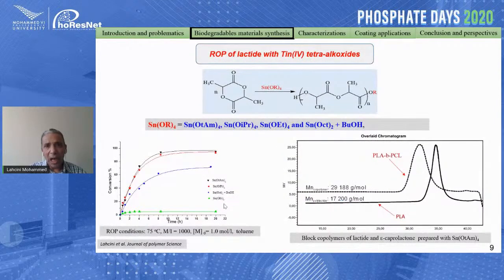In our group, a few years ago, to benefit from the excellent activity of butylated tin(IV) and the low toxicity of tin octanoate, we developed tin(IV) alkoxide. Why? Like butylated tin(IV) alkoxide, we don't need to use any alcohol as co-initiator. And like tin octanoate, with water it is hydrolyzed to tin oxide, which is admitted by the American Food and Drug Administration. We compared its activity with the standard catalyst tin octanoate, and we can observe here that we have really high activity compared to the standard one.